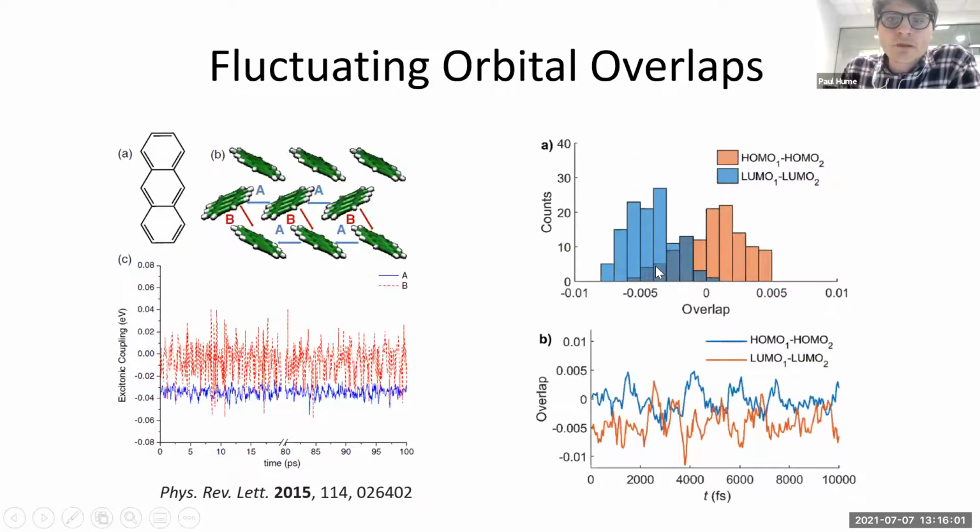The other thing you have to worry about with the couplings is disorder in them. So there's this PRL paper from a few years back, which is pretty well known, which looked at how electronic couplings get modulated due to thermal motion in anthracene crystals. And the big takeaway from that was that the fluctuation in coupling can be pretty wild. And so it's not always that appropriate to simply calculate the couplings like we were doing between crystal geometries.